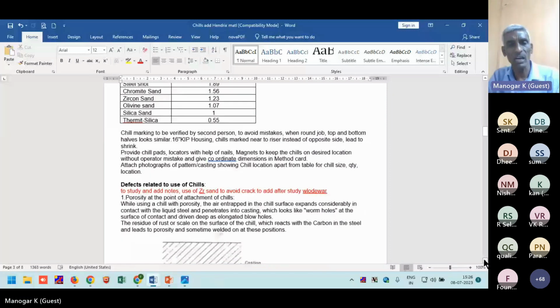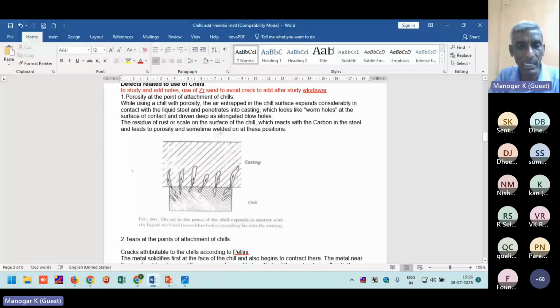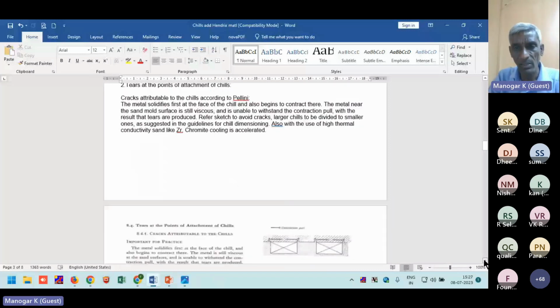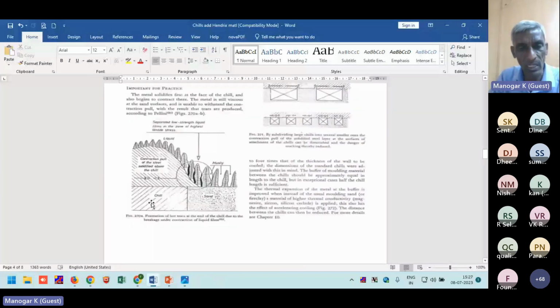So the defects related to chills are, if the chill is not properly ground or coated, then you will have this gas defect below the chills. That is always a problem in chill foundries. And if you are keeping too many chills, then there is a chance of cracks around the chills. So then you have to distribute the chills and keep a proper sand thickness in between chills and proper thickness.